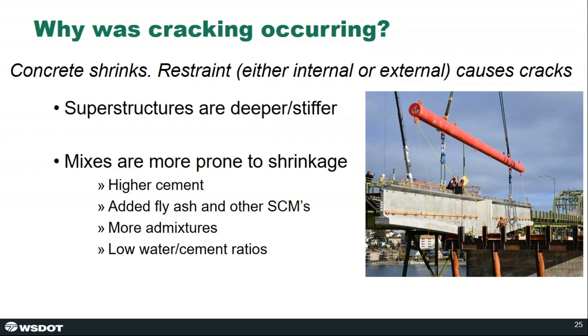Two, we were finding that our mixes were more prone to shrinkage. As we targeted higher cement contents and the use of fly ash and other SCMs, that's potentially leading to more shrinkage overall with the higher cementitious content. There's a wider use of admixtures as well, and it's not always clear how those play together and their ultimate impact on shrinkage of the concrete.